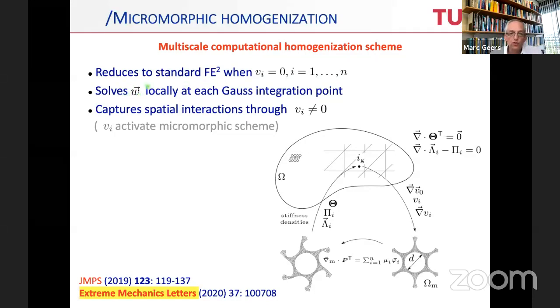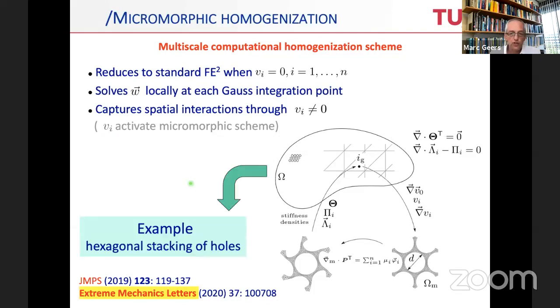Like always, we solve for the fluctuation fields locally at each Gauss integration point. So the micromorphic scheme only comes into action as soon as one of these amplitudes becomes non-zero. Otherwise, it's a regular continuum. So you could state that these quantities Vi, these fields, activate the micromorphic scheme. I will now show an example hereof on a hexagonal stacking of holes, which was published in Extreme Mechanics Letters, which is important to remark since this is an EML webinar.